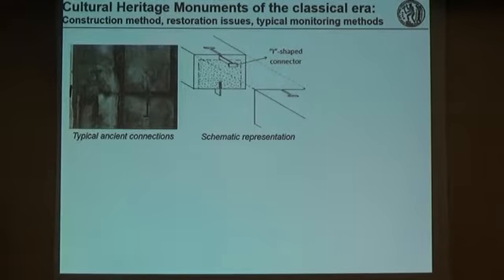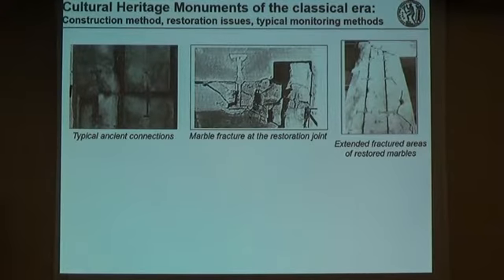Cultural heritage monuments of the classic era are constructed using marbles that are connected together using iron elements, which are placed in specially carved grooves, which were then filled with molten lead. Over the centuries, due to corrosion and also mechanical loading, a lot of those connections had fractured, and there is a project at the Athens Acropolis and at the Parthenon for restoring these fractured